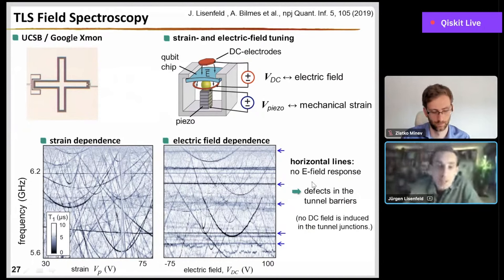Now we can distinguish these signatures as coming from defects on the surface and from those in the tunnel junctions. And you can imagine this is again very nice just to debug your qubit fabrication, to see which part of the circuit is the major contribution to dielectric loss. And we decided to measure this more systematically.